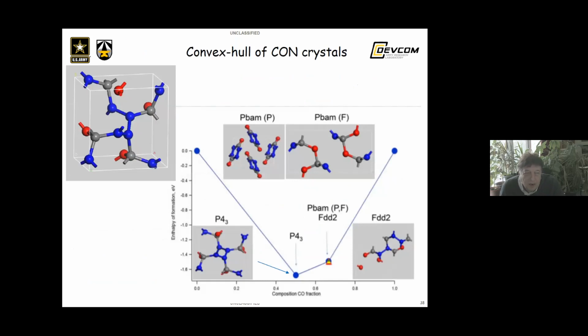Here's a convex hull diagram of a mixture of CON2 compared with other structures. So this is our structure, what we found, P43. And this is the structure corresponding to 2-to-1 ratio, found by Chris Pickard using ab initio random structure search. So these structures shown here are almost the same, but there is slight difference between enthalpy.